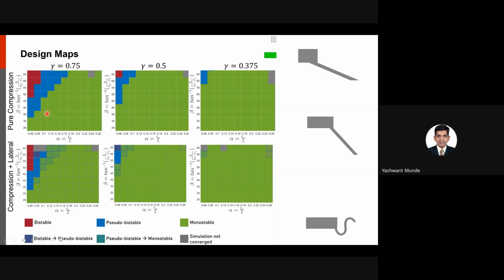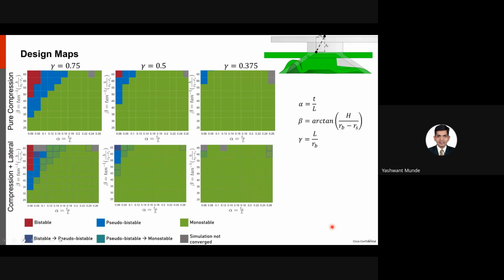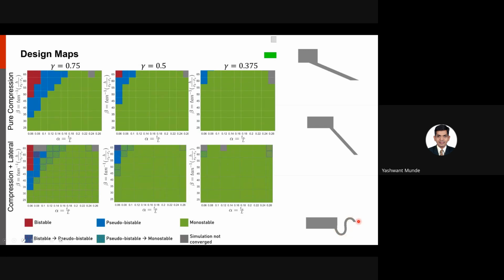And here in this graph, you can see that as alpha reduces, that is, we have thinner structures, and as beta reduces, shallow structures, we have monostable. Also, if we increase the thickness, we have a large range of monostable structures. Now, in red is the bistable behavior, which basically corresponds to very steep slopes and very thin walls. So that is this region. And if you see here, this third case is that we have a very thin wall with a very steep slope. So for these Prony series and for this viscoelastic material, we get a band of geometric parameters where we can achieve this pseudo-bistable behavior.